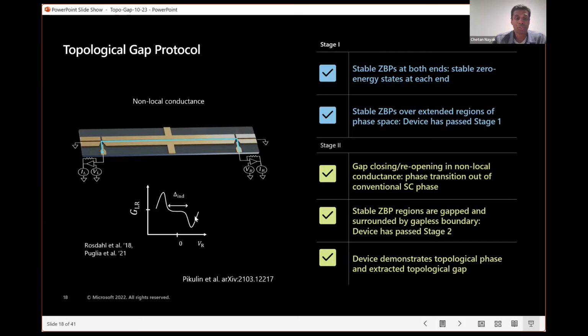The only place where there's a non-zero signal is between the induced gap and the parent gap, because above the induced gap, the charge can go into the semiconductor, but it's below the aluminum gap, so it can't go this way. Because remember, here and here, the semiconductor is fully depleted, so there's only aluminum out here. So it can't go to the left and to the right. The only place the charge can go is through the middle of the wire and come out over here. And that's why the non-local conductance, or GLR, and similarly GRL, is 0 beneath the induced gap. And as the induced gap goes to 0, which is as it approaches the phase transition, this region right here keeps shrinking down.